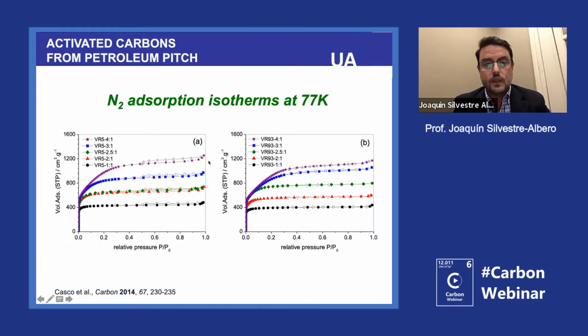So we did nitrogen adsorption isotherms, and you can see that the performance is very similar even if you are with a very low mesophase content or with a high mesophase content. In general, the isotherms look rather similar, and the porosity is also similar. So the main changes are coming from the amount of KOH that you have in the system. If you have a very small amount of activating agent, so a 1:1 ratio, you can see that in both cases the isotherm has a very narrow knee. So this is reflecting that you have narrow cavities or narrow pores in your material.